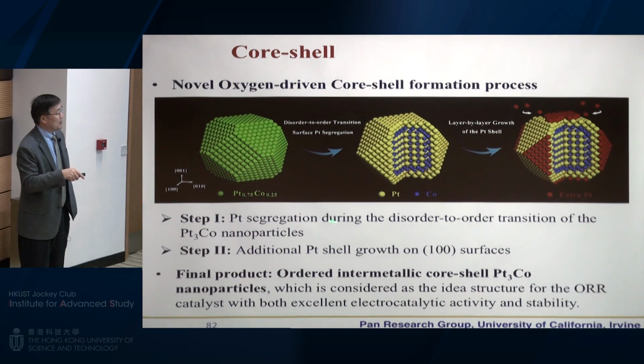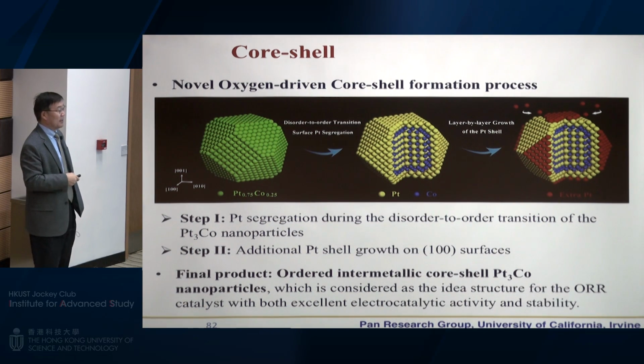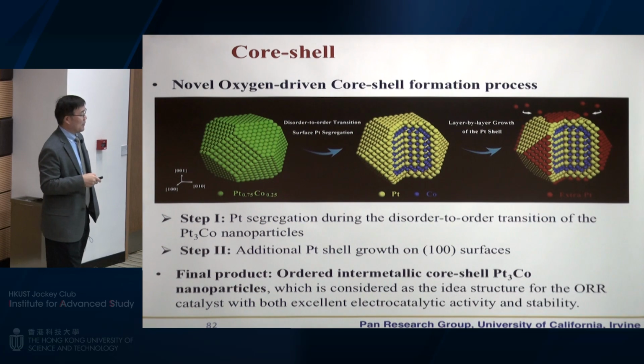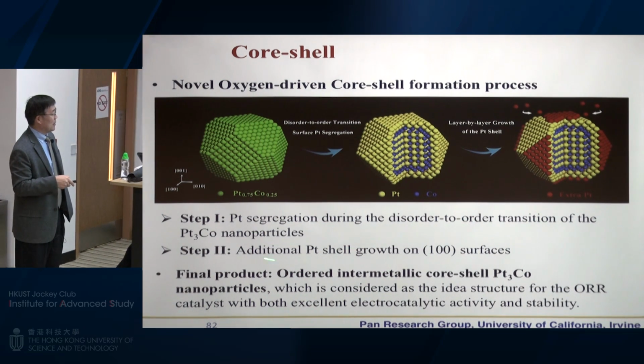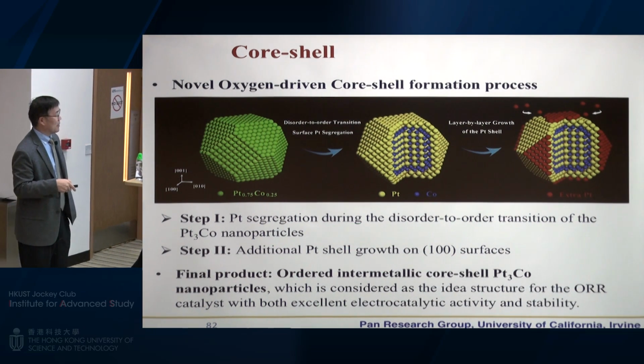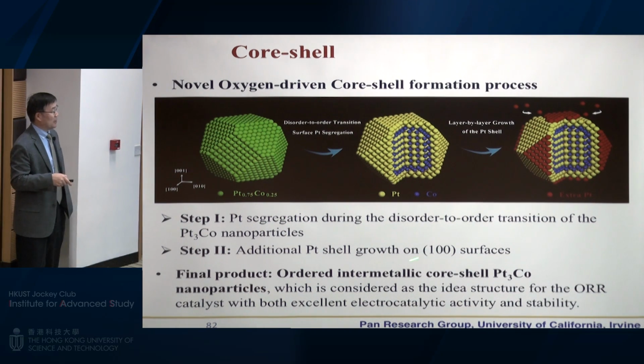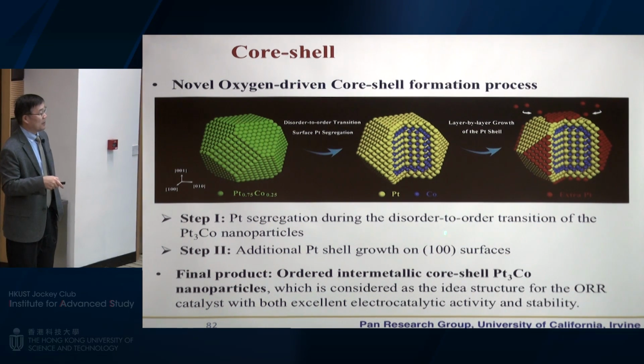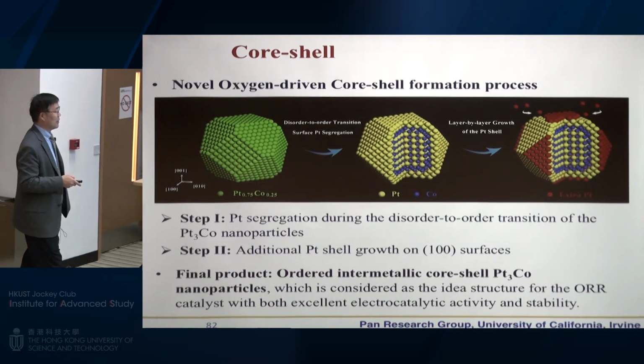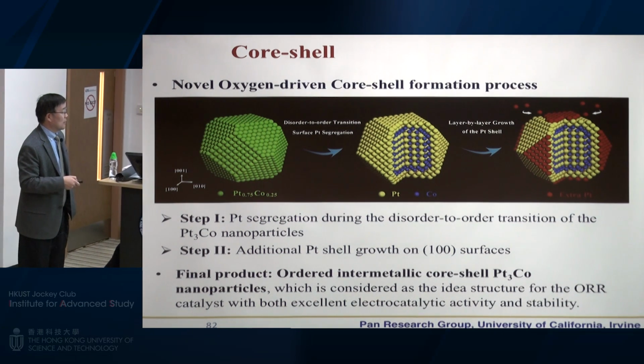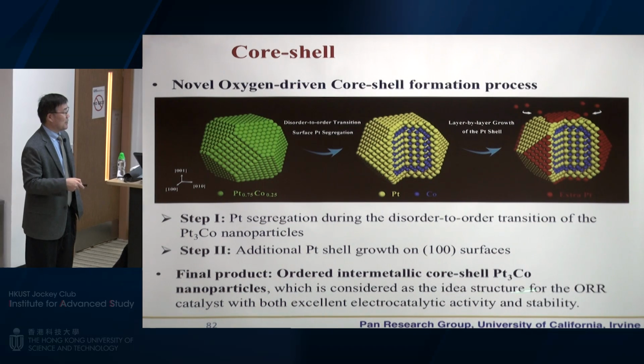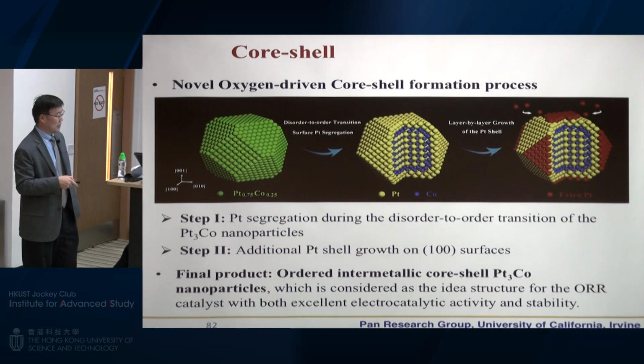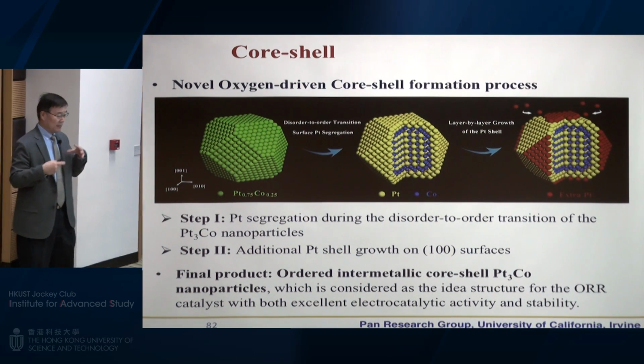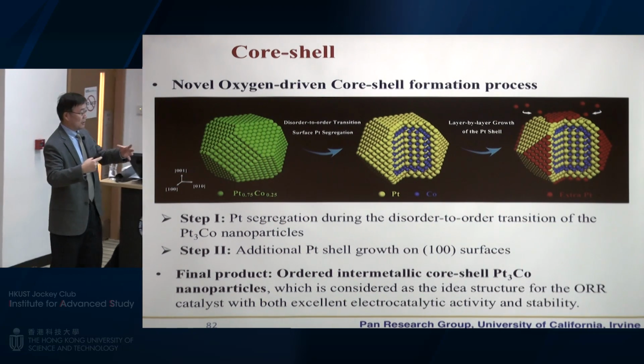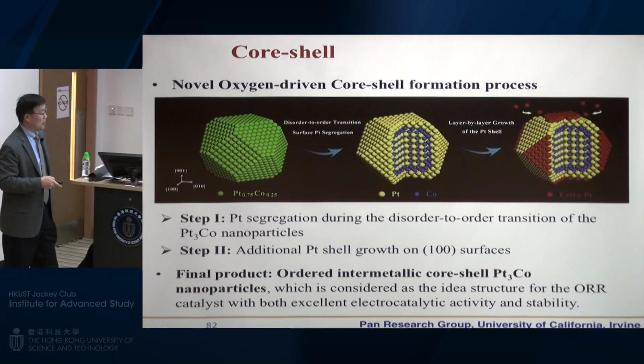The first step is the order-disorder transition that happened at 750 degrees C in the oxygen atmosphere. Then if you lower to 300 degrees C with the same atmosphere, you see additional platinum shell form on the 100 phase, not on other surfaces. So the final product we see during this treatment, we call a core-shell structure: ordered platinum cobalt core with a pure platinum shell.